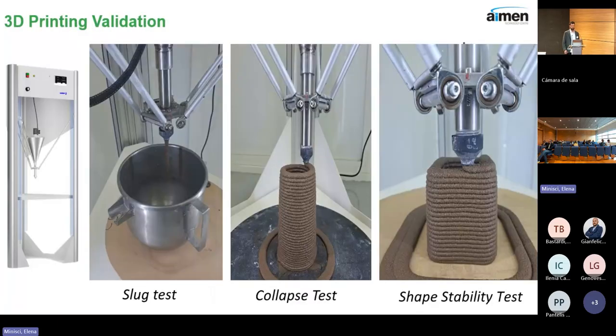And in the next phase of our methodology, when all of these previous tests were fulfilled, we pass our materials to the next phase, which is our small-scale printer, the Delta One. And here we validate our materials through different tests: slug, collapse, and shape stability tests. The first one is very easy. You only have to extrude small drops, so-called slugs. You have to measure the mass average, and with a physical equation, you can obtain the shear stress, and it's very useful for monitoring the quality of your sample before printing.